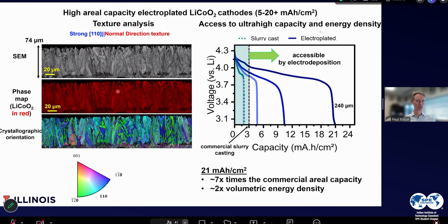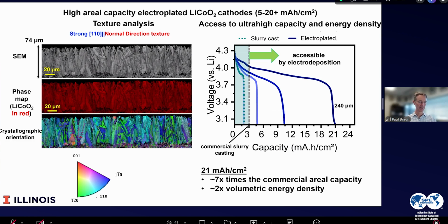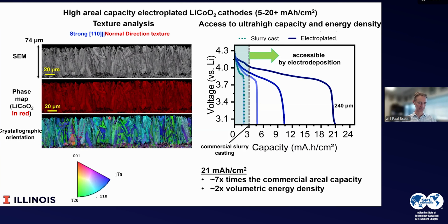If you look at a phase map, it's phase pure, so it's indeed the O3-type lithium cobalt oxide. And if one looks at the crystal orientation, one can see that it's predominantly oriented with the O3 planes parallel to the desired transport direction, or what we will call the 110 orientation. So the O3 planes are primarily running up and down. Because the fast transport directions are aligned this way, one can grow thick electrodes that still cycle.